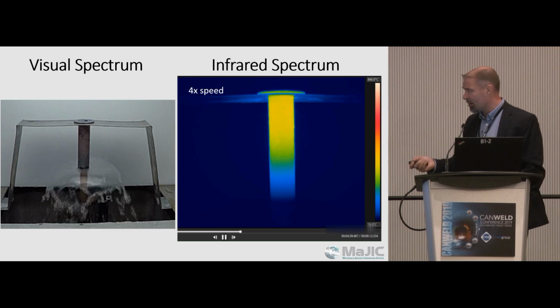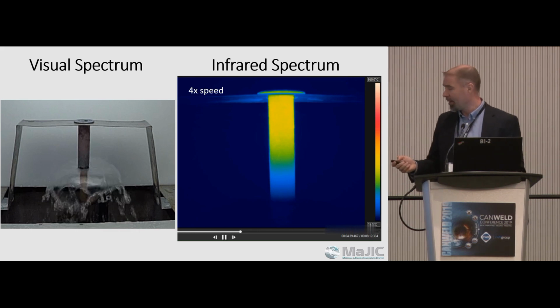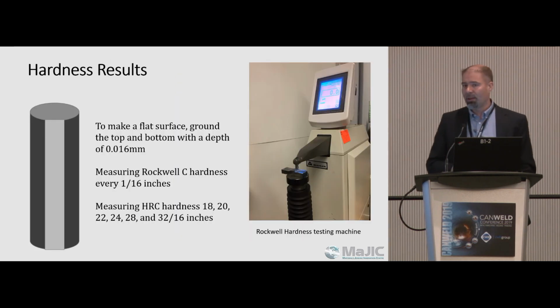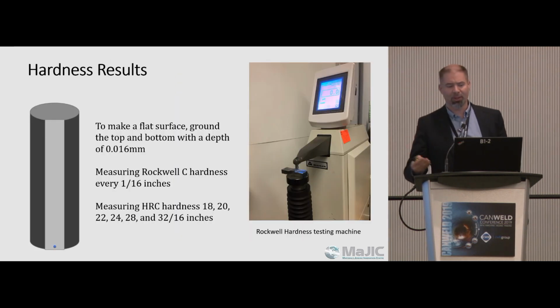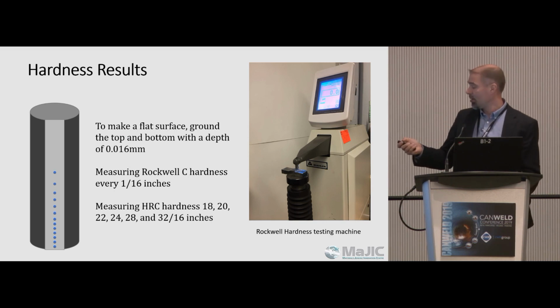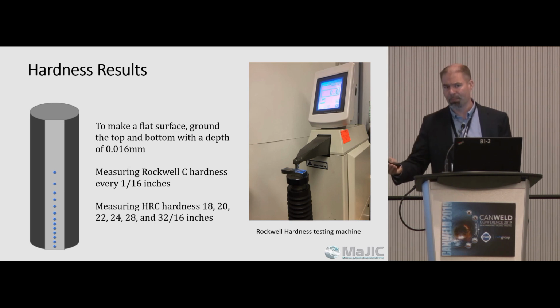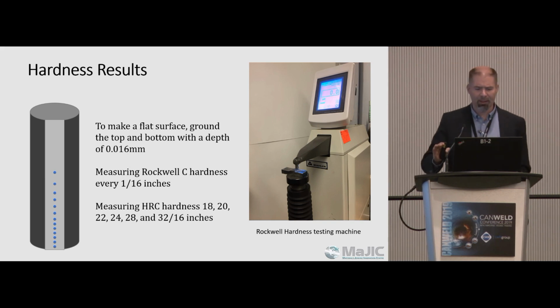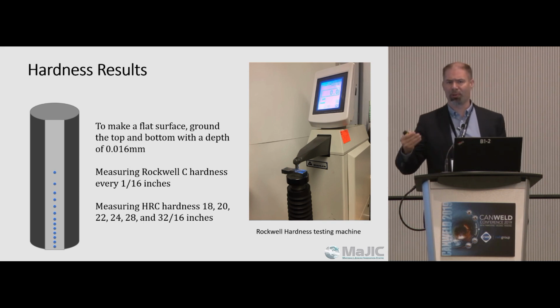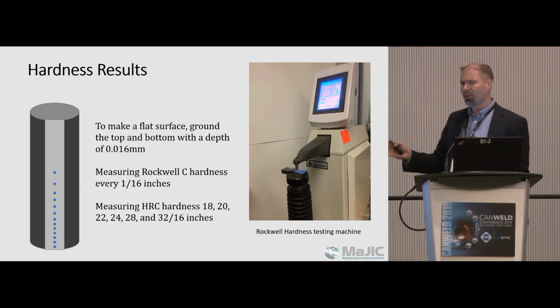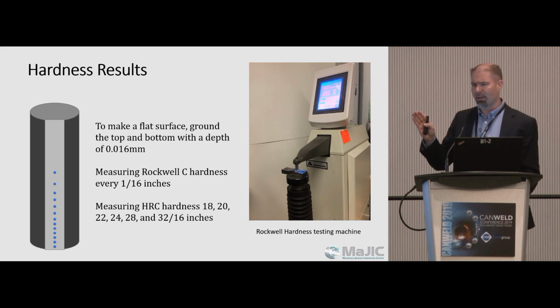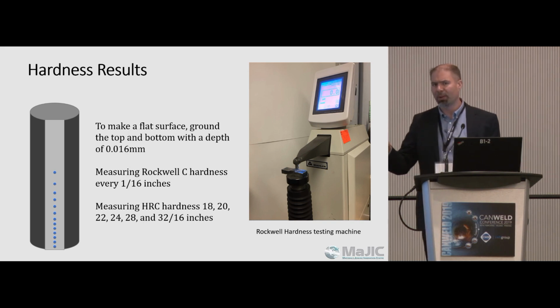So once this Jominy end quench sample is completed, the next step is to examine what the resultant hardness is. So the sample's prepared, and then step by step along the coupon, hardness is measured. This is nothing extraordinary, nothing new. But what we're doing is looking at correlating this hardness data with the thermal imaging video.